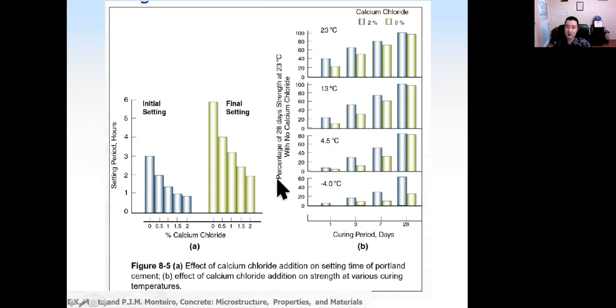And here's another example. This is the percentage of 28-day strength as a function of percentage of calcium chloride, at different temperatures. So we can see when we add calcium chloride, the early age strength at 1 day, 3 days, 7 days, up to 28 days actually increases. So again, the major benefit of accelerator is to increase the early age strength.